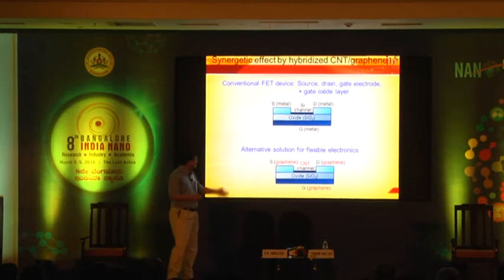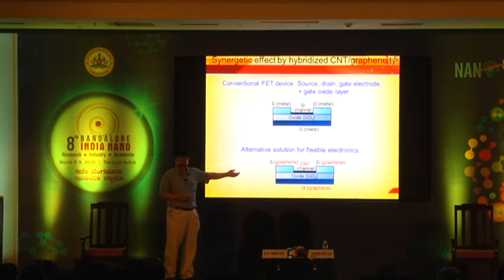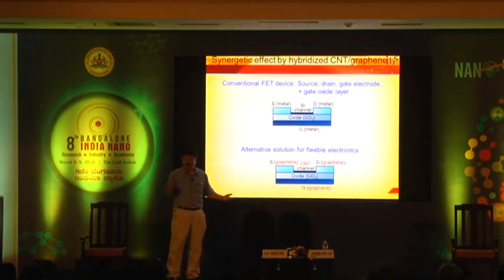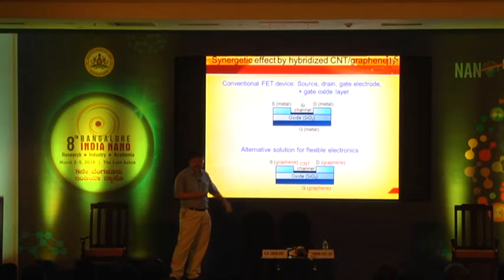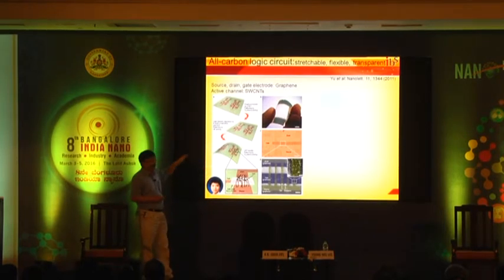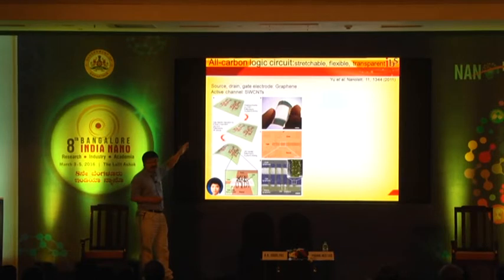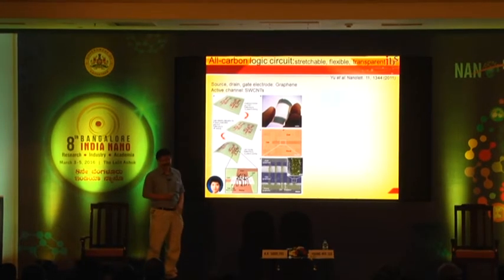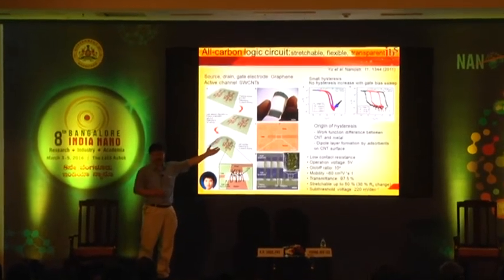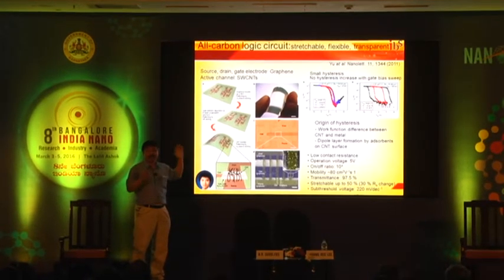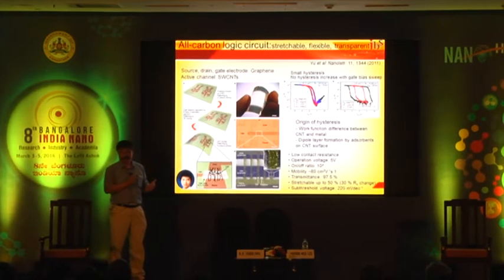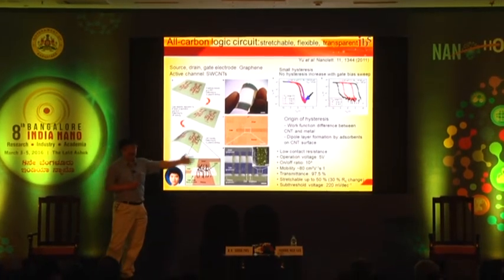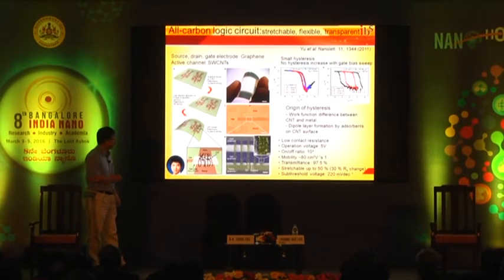We need stretchability. So we came up with an idea: we can simply replace this metal with graphene electrodes because it's highly conductive, and we can use semiconducting carbon nanotubes as the channel material, and then we can demonstrate it. With this, we first tried to fabricate all these devices on a PET substrate and simply tried to bend it. So it actually works. The device works perfectly, even with less heat stress. I'm not going to discuss details, but this all-carbon electronics works with all reasonable numbers for the device characteristics.